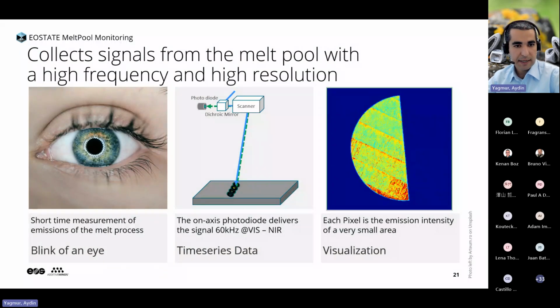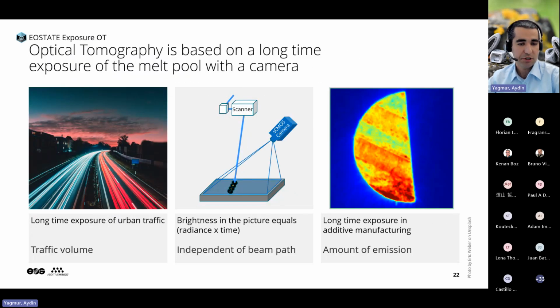For melt pool, as I said, it is focusing on the laser exposure area and getting the location information from the scanner and created this compound picture. So all this information that we see on the right side was recorded by the photodiode, and the location information from the scanner, we created this compound picture. And what we see here is, for example, in this area, an overheating caused by short vectors, and we see the behavior during melting. Let's look at the same part, but this time the OT picture.